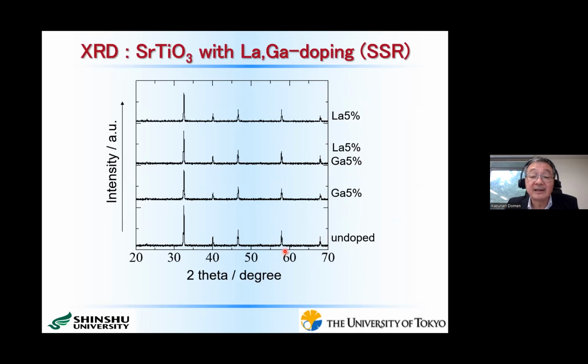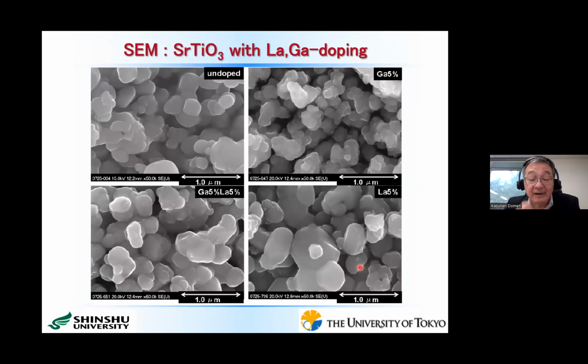However, as you see here, in these X-ray patterns we observe only a single phase of the perovskite type structure, and there seems to be no difference. Even after observing the SEM images, this is the undoped sample, this is gallium 5%, lanthanum 5%, gallium and lanthanum 5%, we are not able to distinguish them from each other.